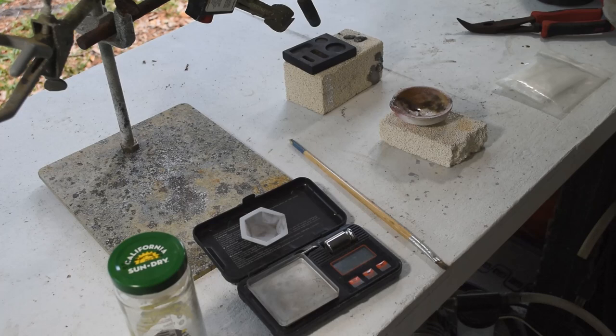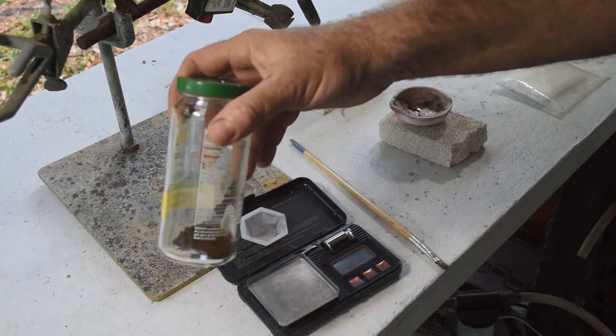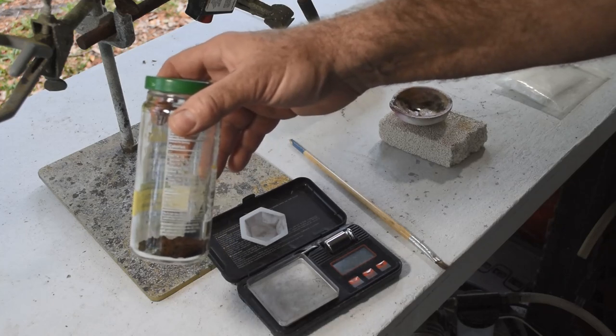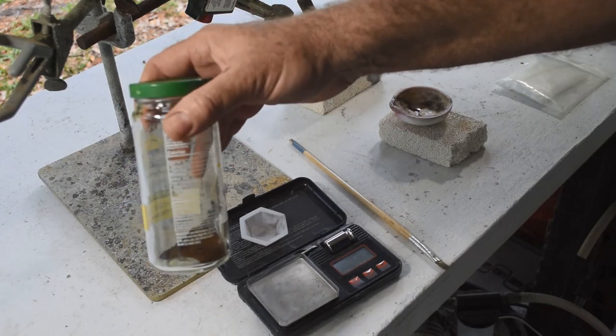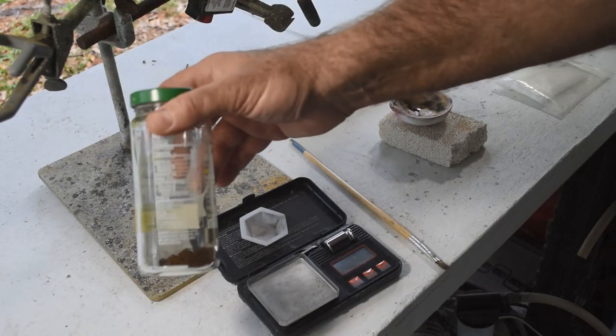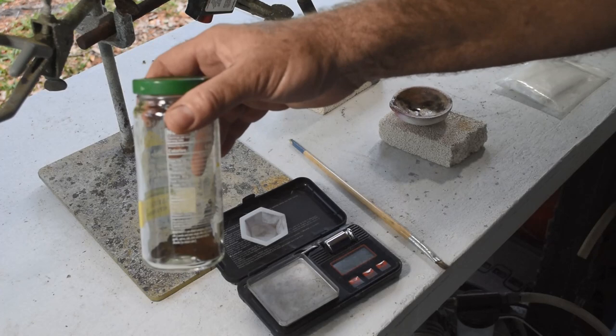Hello scrappers, Mike here. Welcome back to my channel. Today I'm going to melt some of my gold. I've got some gold here that I have triple refined — it's actually been precipitated from solution more than three times. The first time doesn't count generally because it usually comes out of a very dirty solution. So what I do is I redissolve it in aqua regia, filter it well, then re-precipitate it with SMB. Then I'll re-dissolve it in aqua regia again, filter it very well, and re-precipitate it with copper or iron sulfate. Then I'll re-dissolve it in aqua regia one more time, re-precipitate it with SMB, give it multiple boils with hydrochloric acid and then distilled water, and then I consider it clean enough to melt into bullion.